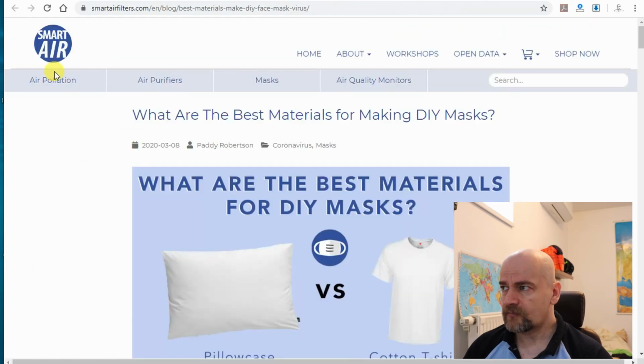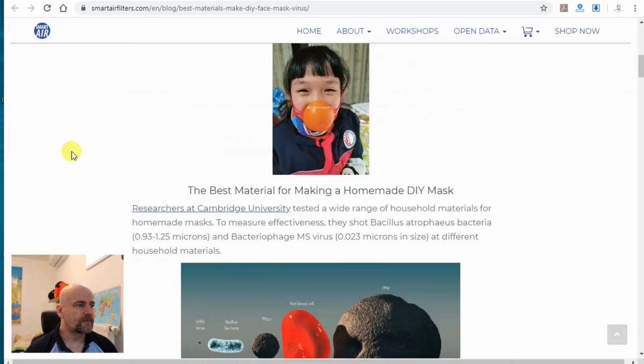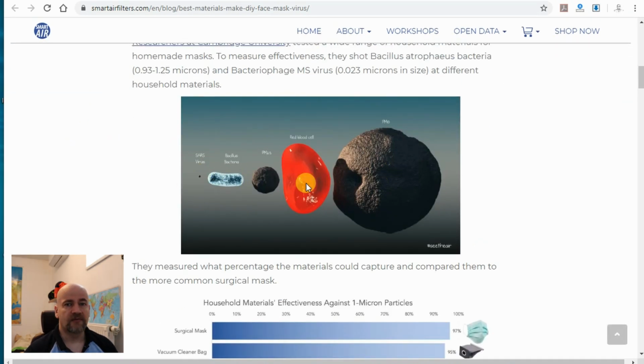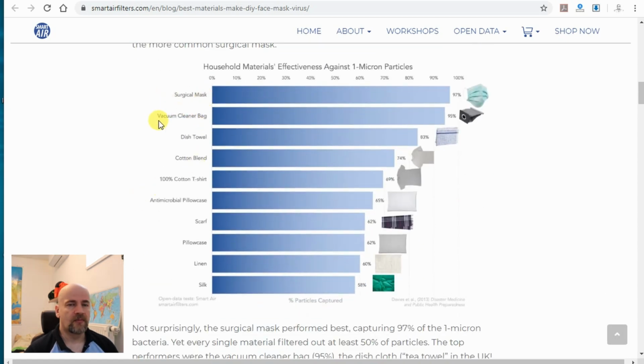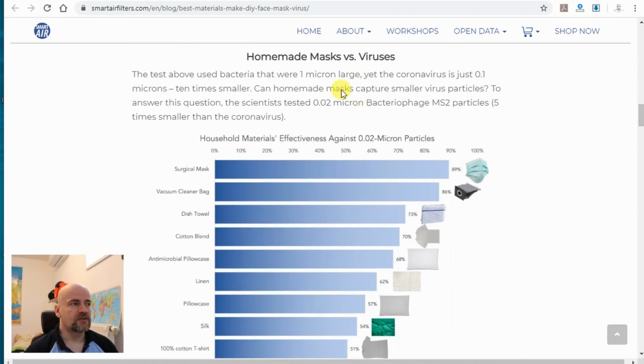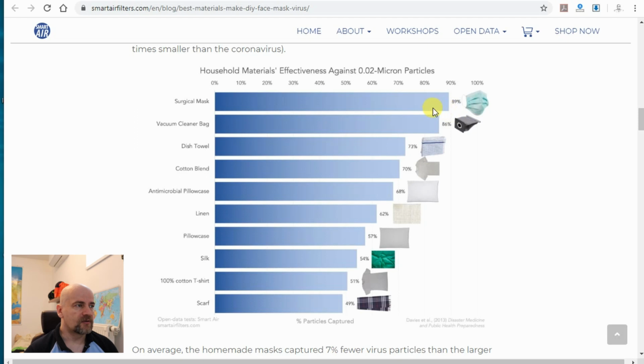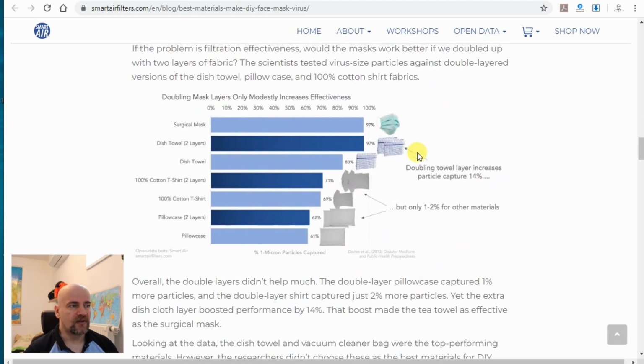Another very interesting article is from smartairfilters.com. Here you can see the comparison of the size of different particles. And again, a surgical mask compared to the vacuum cleaner bag: very similar efficiency. Next in this list is the dish towel and similar. This is efficiency against 1 micron particles. And the next comparison is again 0.02 micron particles. So again, you can see, for example, the surgical mask filter 89%. Vacuum cleaner has an efficiency of 86%. Again, third is the dish towel. But very interesting information is this: if you use two layers of dish towel, then it has similar efficiency to a surgical mask.